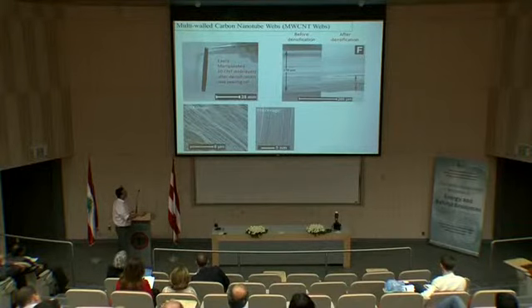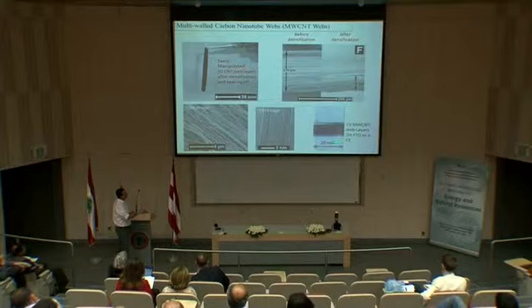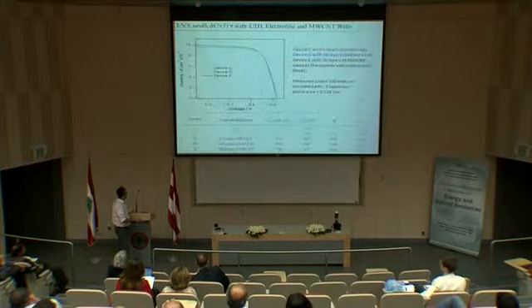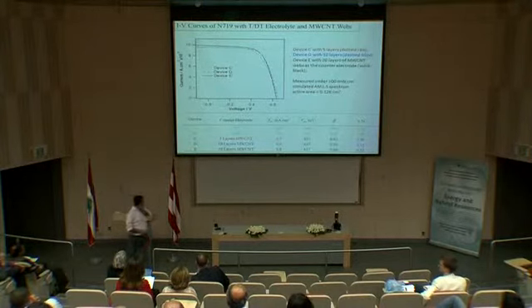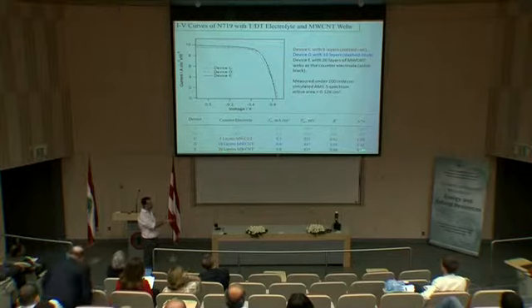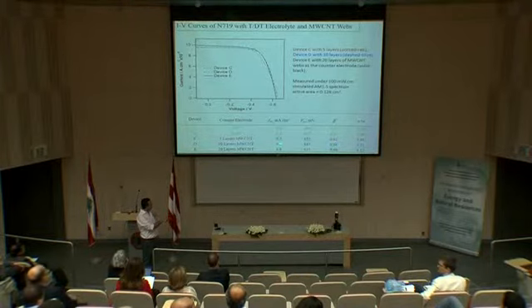And this is a photo of the electrode that we made in our lab. When we made the cells with these, with 5 layers, we did not have to go to 50 and 100 layers. With 5 layers, we got 3.86. 10 layers, 4.11. And 20 layers, 4.12. You see, the fill factors got much better. Currents are approximately the same for the 5, 10, and 20, but they are much higher than the black one.